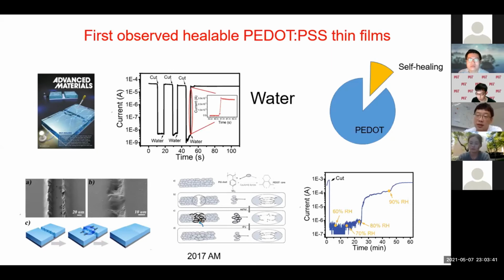If you make them very thick, they can just push back, because for example, you cut a line made of sand, right? The sand comes back because of viscoelastic properties, like hydrogel. But for a thin film, for example, 1 micrometer thick or 10 micrometer thick, still, I mean, it's still not very thin. So they still have the chance to come back if it's very elastic, because if it's very thick, it becomes a little bit soft. There's water inside.